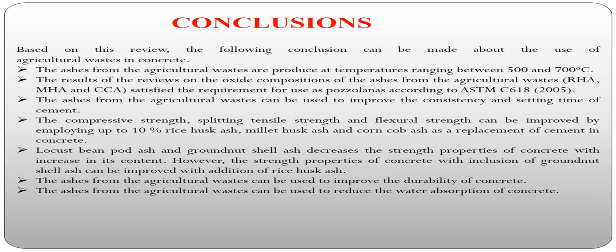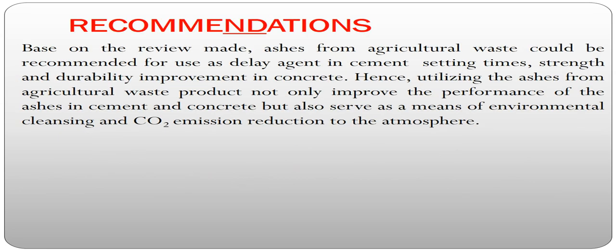The compressive strength, splitting tensile strength, and flexural strength can be improved by employing up to 10% rice husk ash, millet husk ash, and cob ash as a replacement in cement. Locust bean pod and groundnut shell ash decrease the strength property of concrete with increase in their content. However, the strength property of the concrete with inclusion of groundnut shell ash can be improved with addition of rice husk ash. The ash from the agricultural waste can be used to improve durability of concrete. The ashes from the agricultural waste can be used to reduce the water absorption of the concrete.